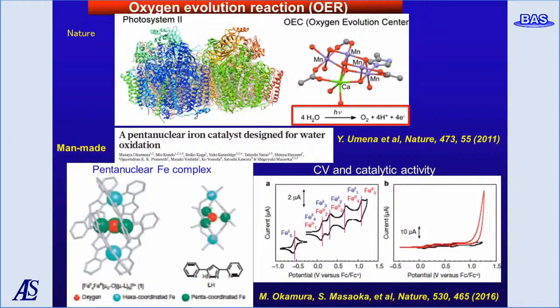When water was added to the complex, an oxidation catalytic wave with a large rise of the current around 1 volt was observed, indicating that these iron clusters act as the oxidation catalyst for efficient water oxidation to dioxygen. Thus, it is possible to evaluate catalytic activity by using electrochemical methods such as cyclic voltammetry.